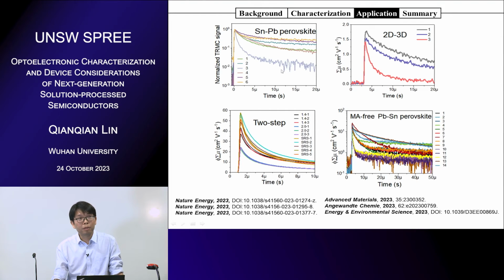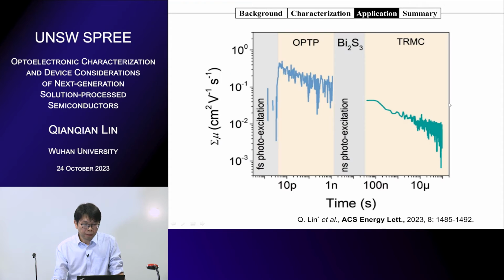So we collaborate with a lot of groups in China or overseas, and we recently helped them publish some results for perovskites, both for tin lead perovskites and also some 2D perovskites. So it also works for the perovskite community very well. And if we combine optical pump terahertz-probe spectroscopy and microwave conductivity, we get more information